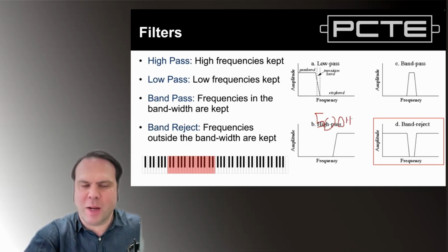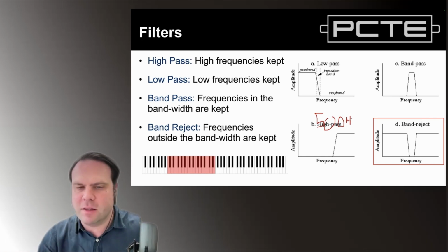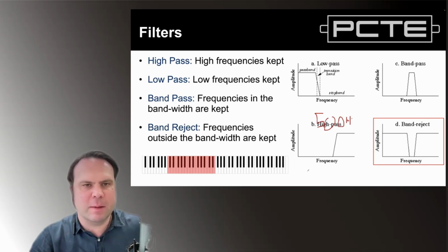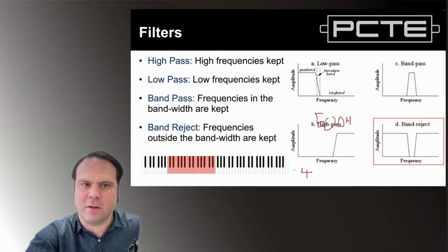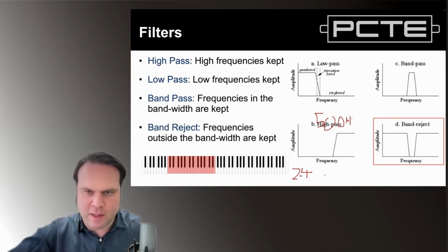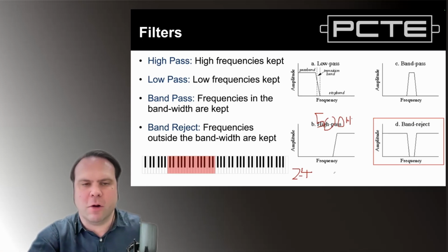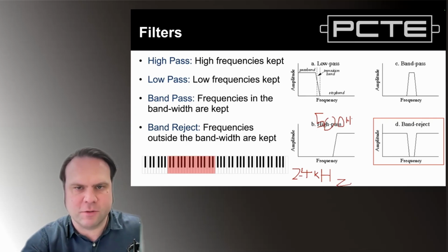If you're testing a reasonably thick element, if you're just doing plate testing like 150 millimeter thick, it may be appropriate to go as high as 24,000. If you're doing relatively thin sections, 15 to 25 millimeter sections, that would be an alternative for slightly more constrained testing regions.